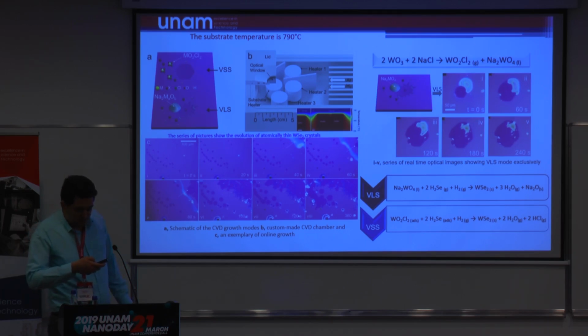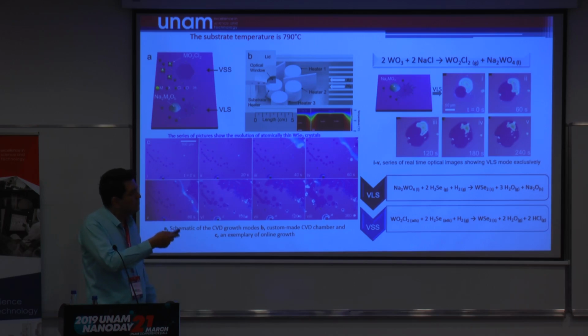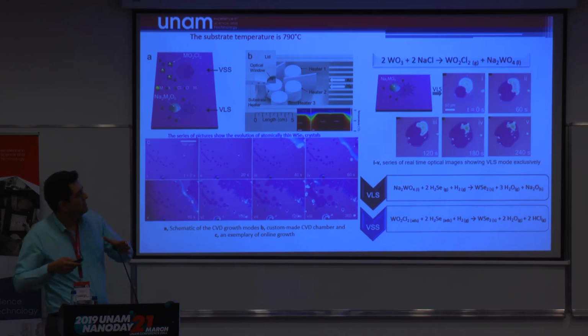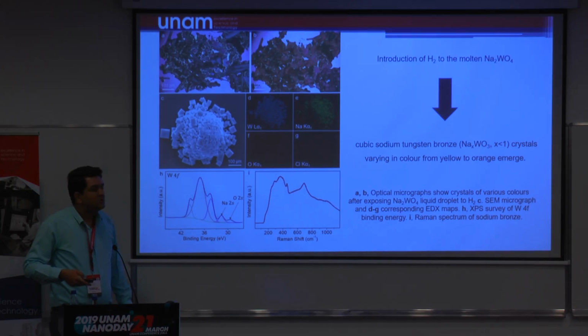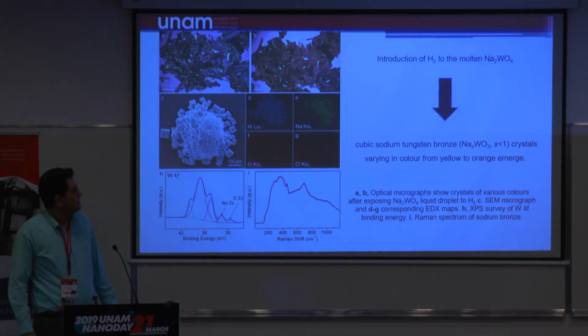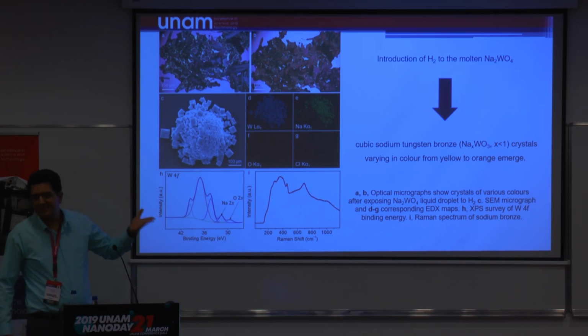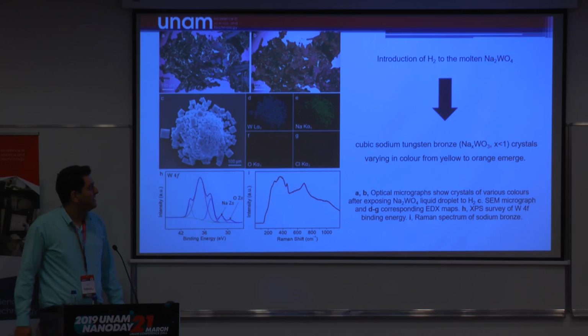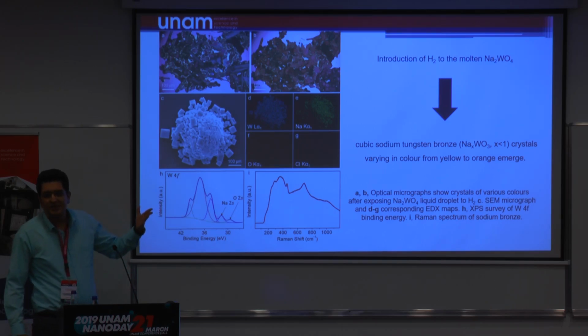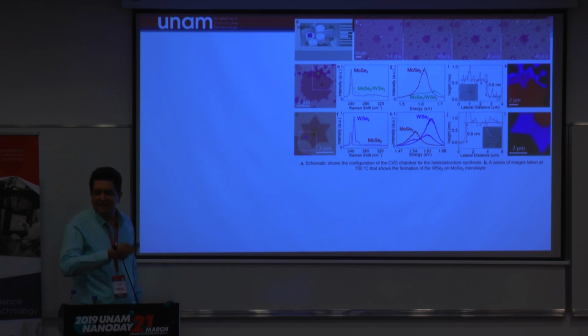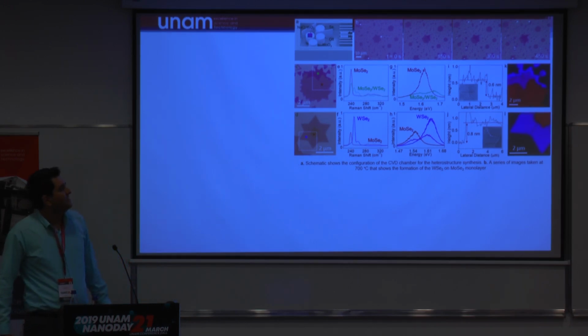By controlling the volatile precursors and intermediate compounds, we can exclusively promote either VLS or VSS. Also, we investigated the effect of hydrogen, which is studied for the first time, as well as the monitoring of real-time growth. We found that sending hydrogen is very critical at some growth stages. Due to the lack of hydrogen, you may end up with sodium tungsten bronzes.